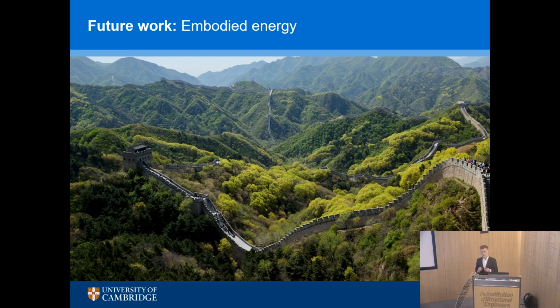So there's been a lot of research, which actually began in the 1960s, saying that we can make carbon fiber from lignin, which is the second most abundant source of carbon on the planet. And today, I counted it up just recently, so I know the answer, there is 100 million euros worth of funded research going on in the European Union to turn lignin into commercially available carbon fiber. So it's a bio source of carbon. So that's coming. And that is 50% less embodied energy straight away through using the bio source of carbon.